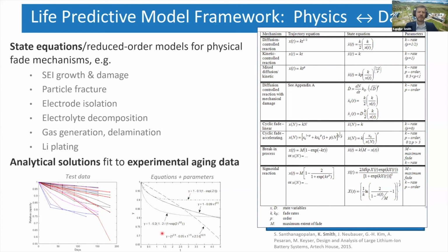So what we do is we fit test data. Right now this is somewhat visual. We're working on machine learning techniques to automate the identification of these individual mechanisms. But you'll see things in data like this blue line. This is a cold temperature degradation where there's a real rapid drop-in, a break-in mechanism. And so we can describe that with an exponential decay term, followed by perhaps some other rate of fade, which is slower. There's others like the purple here, which look like the square root of time, so we can fit that with the square root of time fade.